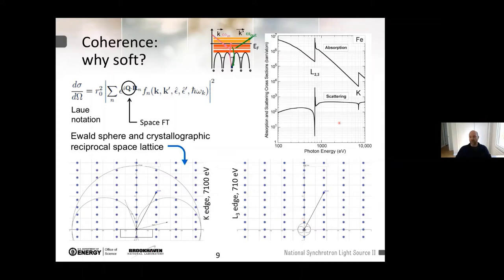The other advantage is what I already showed before. Apart from the fact that the scattering is much smaller than the absorption and other cross-sections, as I was trying to show before, the difference between the K resonances and the L resonances for transition metals is massive. It's at least one order of magnitude or more. So there's obviously an advantage in terms of the strength of the signal and other characteristics that I will show in a moment to move to soft.